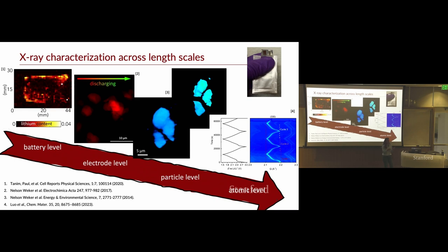doing things with porosity. So we explored coating dual layers of the anode material. Making a very dense layer at the bottom near the current collector with small anode particles that had a smaller packing density, essentially. And then on top, make a slightly porous layer with larger particles. And so you could get electrolyte infiltrated into the whole anode material and utilize the anode better. Because what we found is we were just utilizing the top, you know, few microns of anode material.